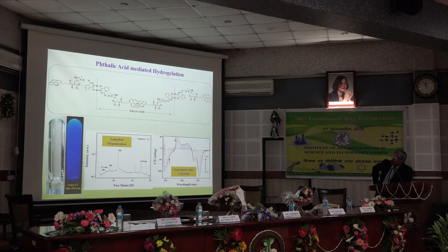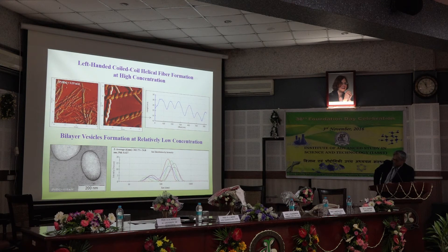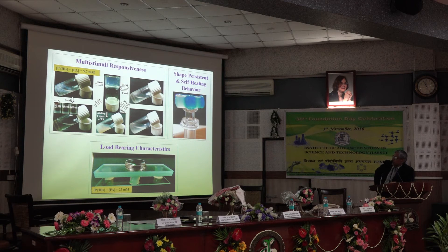We have now made a molecule which can detect only phthalic acid. You can see this molecule is totally transparent, but when we shine light on it, it gives you this kind of glow. So we can actually detect — if you have a small amount of phthalic acid impurity, that can be detected at the nanometric level. And you can see they are structured by various types of force microscopy — they form helical fibers and different kinds of structures. These are self-standing materials.